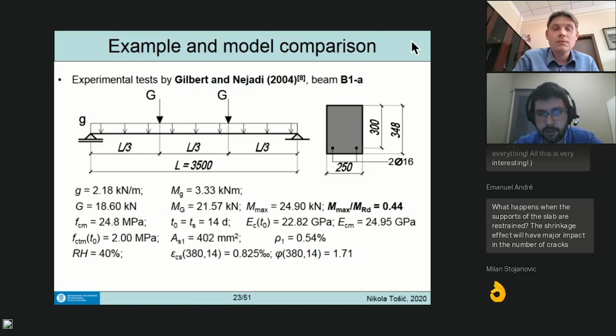This is the cross section, 250 millimeters by 348 with an effective depth of 300 millimeters and 2 number 16 bars. This is the self-weight, the loads, and moments, and the maximum moment was 44% of the section resistance. So the load is relatively realistic for service loads. Compressive strength was not so high, a cylinder strength of 25 megapascals, loaded at 14 days and cured until loading. This is also important for shrinkage: except for basic shrinkage, there was no development of shrinkage until that time.